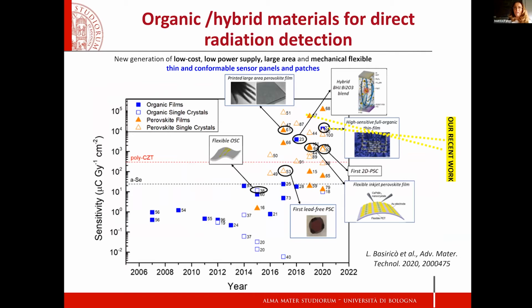This view is quite full of information, but I wanted to show you the steep increase in performance of organic and hybrid materials used for the direct detection of high energy radiation. So we're not talking about solar cells, nor photodiodes, but really high energy radiation detectors here. The figure of merit on the y-axis is the sensitivity, which is one of the most important, not the only one, used for characterizing the performance of radiation detectors. In orange, you see perovskite. In blue, you see organics. You definitely can notice the strong and steep increase, both in the thin film and in the single crystal form.